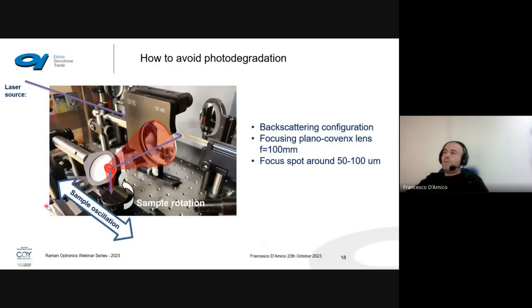How can we avoid it? This is what we use in our system. We have the laser source, we have the macro system, and we have sample oscillation and sample rotation. We are in a backscattering configuration, and the focus spot is around 50-100 microns, and therefore photodegradation can be avoided.